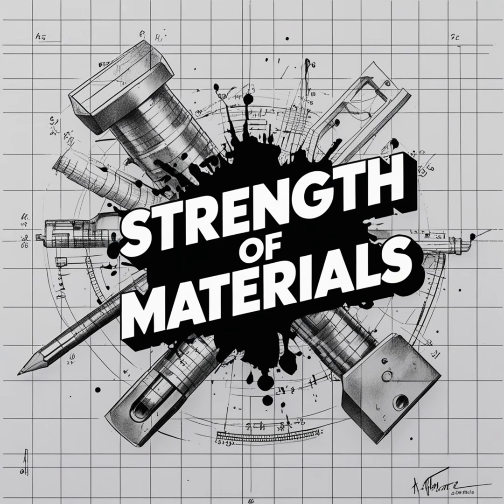But if I'm building something that only needs to survive 100 massive violent impacts? Then you are operating before the crossover point in the low cycle regime. Here, plastic strain dominates the damage. The ductility of the material controls its performance. You do not want a hard metal. You want a soft, forgiving, ductile metal that can stretch and absorb the energy without instantly tearing.